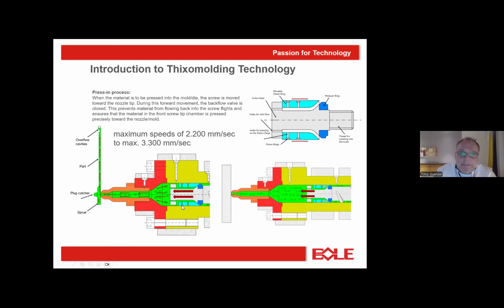Also the speed in Thixomolding technology, when we move forward with the screw, is much lower compared to die casting. In die casting, they run between 5,000 millimeter per second, sometimes up to 8,000. We run normally between 2,200 millimeter per second and 3,300 millimeter per second. That depends on the semi-solid fraction.